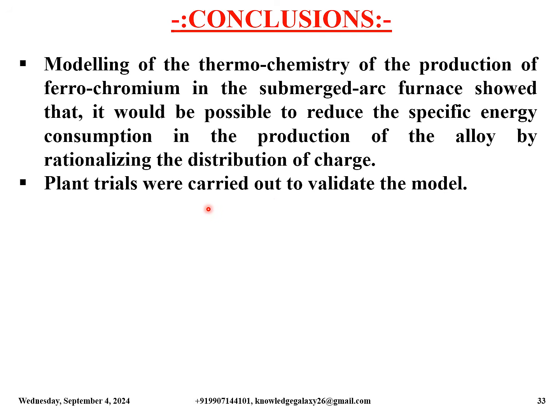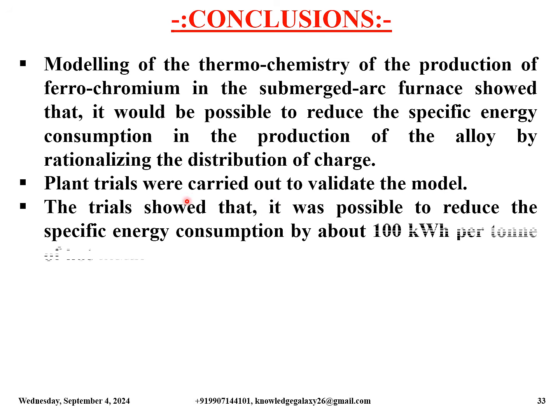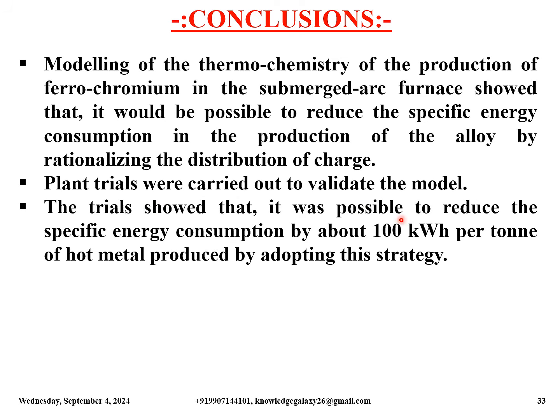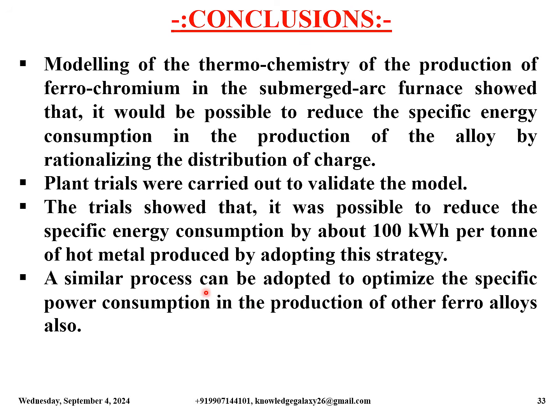Plant trials were carried out to validate the model. The trials showed that it was possible to reduce the specific energy consumption by about 100 kWh per ton of hot metal produced by adopting this strategy. A similar process can be adopted to optimize the specific power consumption in the production of other ferroalloys also.